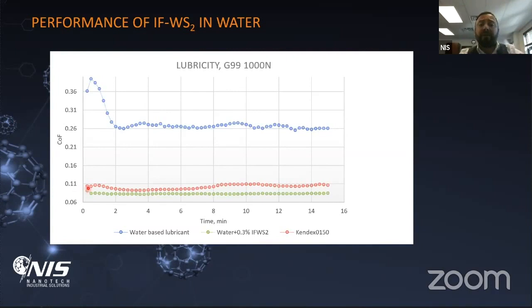But then you can compare it to Kendex, again, the same oil, Kendex 150, a group 2 oil. So friction is much better because it's oil. And with 0.3% of particles and 99.7% of water, you can see that friction is even better than oil. So what are we talking about here? Are we really saying let's replace all the oil with water? No. Also, that's a very interesting discussion. Of course, you can add viscosity modifiers and all the other different additives to make a finished product, but the potential of this is very big.